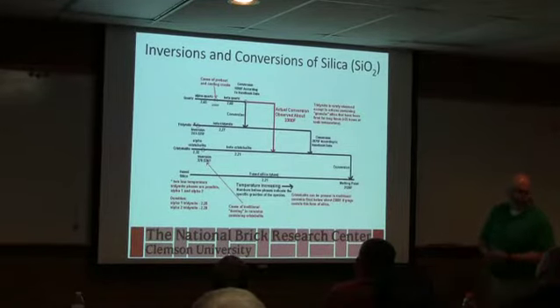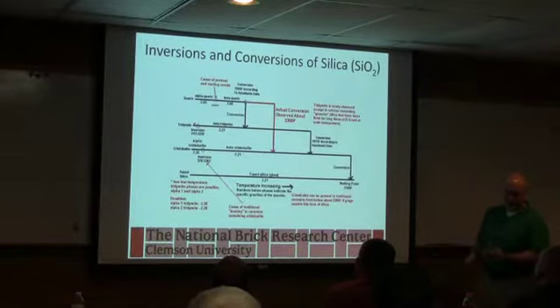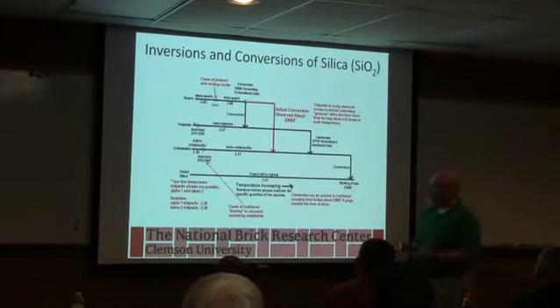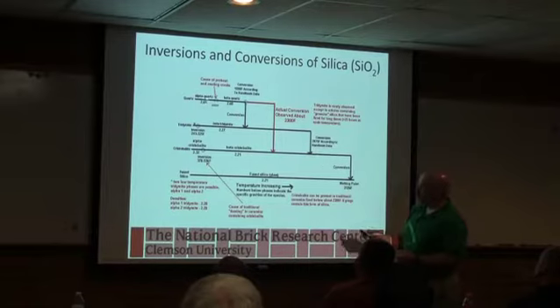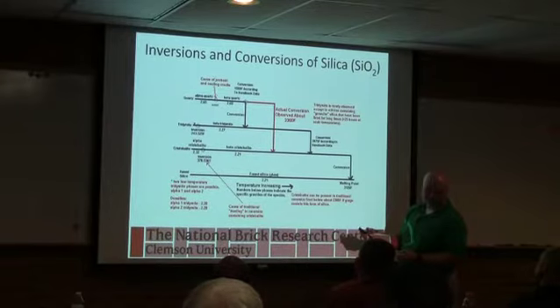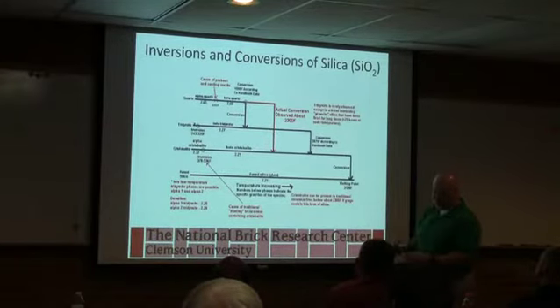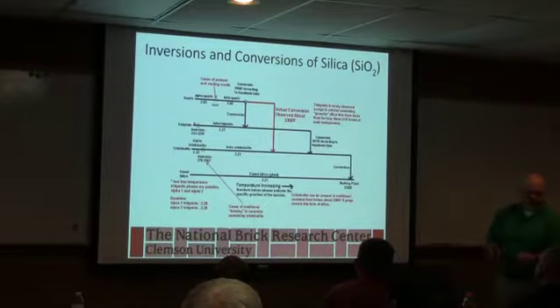Okay? So I've seen brick with very low compressive strength. And you start looking at the cooling zone, and because of the way the fans are positioned, they go through this several times in the cooling zone. And you're doing damage every time you go through that inversion on cooling. You just can't help it because of that conversion.